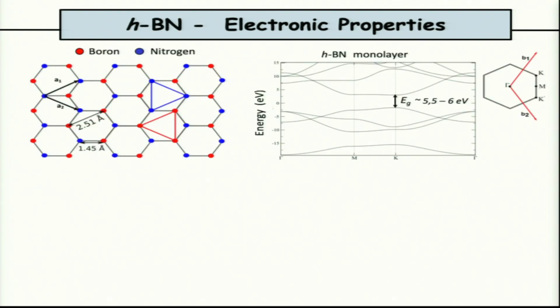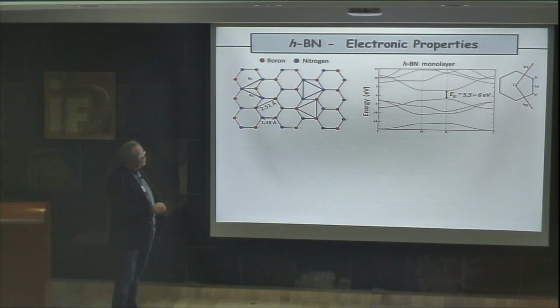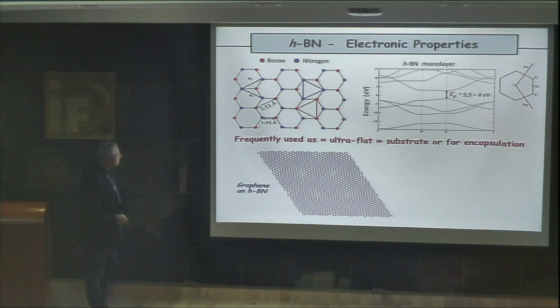In the case of boron nitride, you still have two atoms per unit cell, but they are not the same. So you have one boron and you have one nitrogen. And the fact that you just change the nature of these two atoms leads to a completely different situation. So here you see that from the electronic point of view, you have a clear insulator with a 5.5 to 6 eV band gap. So the electronic properties are completely changed just by modifying the nature of the atoms. So in fact, in a simple tight-binding picture, if you just modify the on-site energy of these two atoms in the unit cell, you will get directly this band gap.